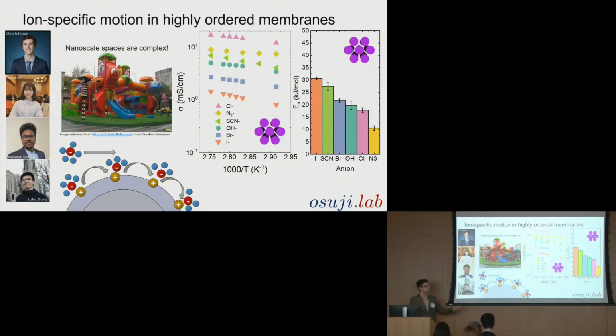And what I'd like you to get from these graphs is that there are differences within our materials. You can see an order of magnitude difference between the fastest and the slowest of our membranes, and then there are some that are significantly hampered, very hard to get moving. They are stuck to those walls within the different membranes between the different ions. And the conclusion that we draw from this is that we can hypothesize that the polarizability, how hard it is or how easy it is to move the partial charge to one area of this ion, will allow it to cling to the wall differently and will be either more stuck or less stuck. This can be used to separate complex mixtures of different ions. And, it teaches us a bit about the ion surface interaction.